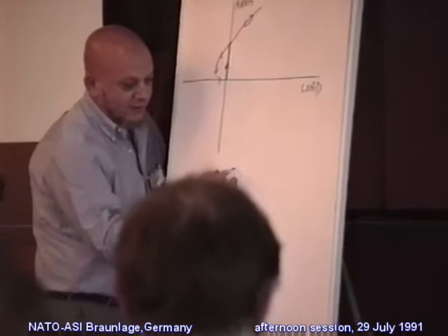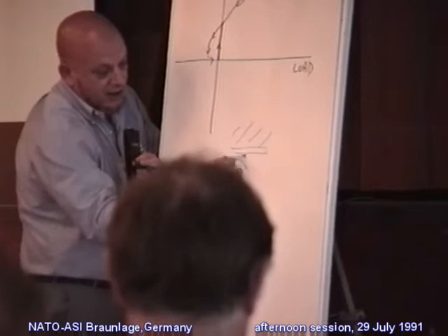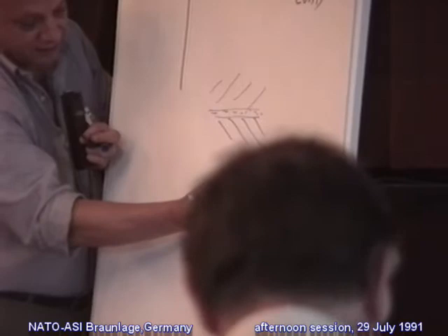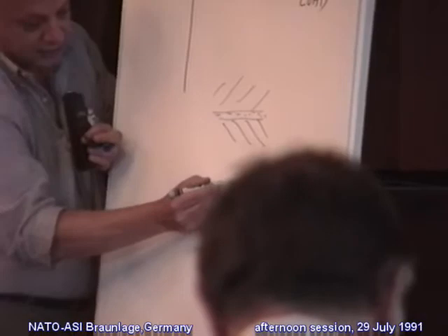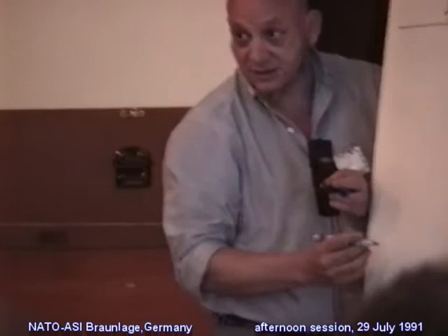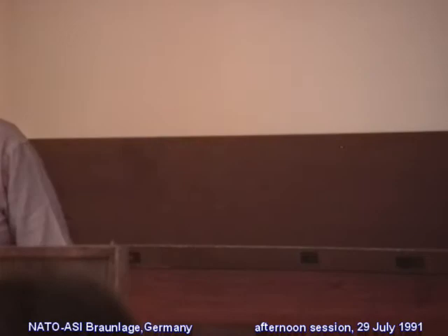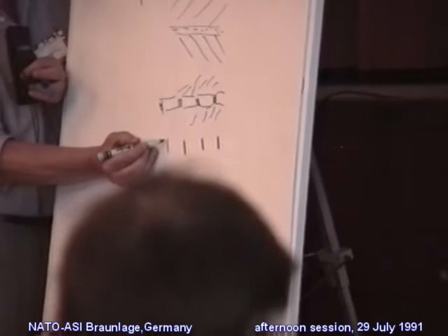Maybe I'll make a picture. If I start from these two surfaces here, and this is the imaginary point where they're going to separate, they can start separating by, say, this is one surface and the other one, and I will start to form these kind of little necks between them. Now I have these necks of material between them, and this is a vacuum here, nothing in between, or air, if you wish. As I go further on, this will thin down to very narrow necks. And the material, if I do it very slowly, will reorganize itself in a reversible manner. And I won't have any dissipation going into here.